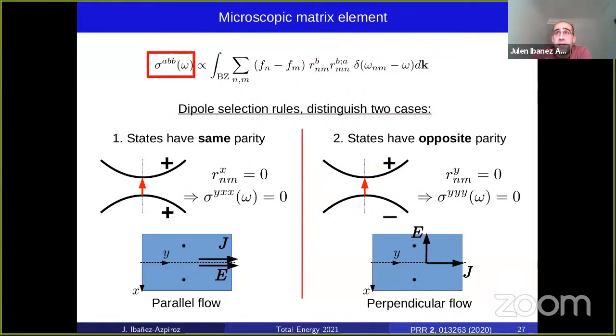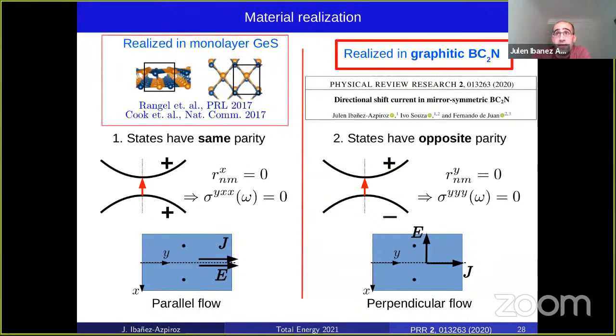And what does this mean in practice? Well, combining this with the shift current expression, dipole selection rules imply that in one case, the current can only flow parallel to the field, while in the second case, the current must flow perpendicular. The first situation is what takes place in monolayer germanium sulfide, which was analyzed in these two works. And the second situation that we have shown is actually taking place in BC2N.